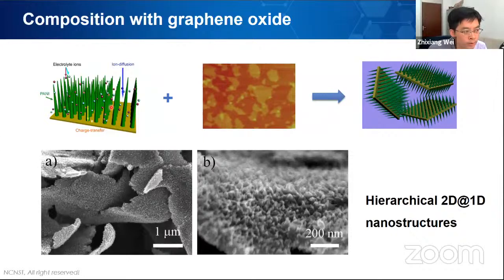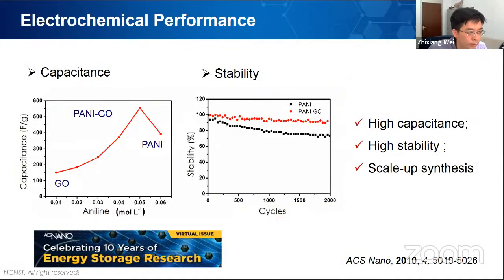We can grow these kinds of nanostructures on two-dimensional materials to get hierarchical 2D, 1D nanostructures. With this, you can see not only their capacitance but also their stability really increased compared with the traditional disordered nanostructures and also the single component of graphene oxide. With this, we can get a material with high capacity, high stability, and scale-up synthesis because the synthesis